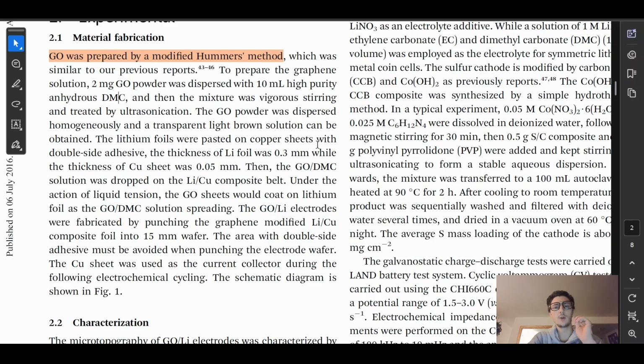The lithium foils were pasted on copper sheets with double-sided adhesive. The thickness of the lithium foil was 0.3 millimeters, while the thickness of the copper sheet was 0.05 millimeters. Then the GO/DMC solution was dropped on the lithium/copper composite belt. Okay. Under the action of liquid tension, the GO sheets would coat on lithium foil as the GO/DMC solution spreads. The GO/Li electrodes were fabricated by punching the graphene modified Li/Cu composite foil into 15 millimeter wafers. So this is the final electrode that they use, I think, for the battery tests.